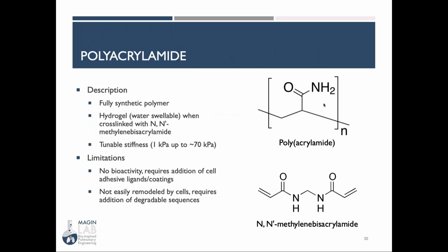So polyacrylamide is a fully synthetic polymer that we can cross-link to create a hydrogel that's hydrophilic and swells with water. It has a tunable stiffness. We can tune it anywhere from 1 to about 70 kilopascals. And just like other fully synthetic materials, it inherently does not have any bioactivity. It requires the addition of cell adhesive ligands or coatings, and it's not easily remodeled by cells. So again, it requires the addition of biodegradable sequences if you're interested in having it be remodeled.